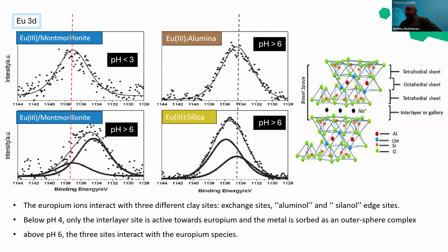So then what they decided, they did the same experiment on alumina and silica to mimic those two edge states that I was mentioning, with a high pH state. They found out that the europium deposited on the alumina is giving the peak at 134. And then in the silica, it is also giving 134, but it is also giving that 136 eV. So based on these two experiments, what they found out is that when the pH is high, the europium is binding in the interlayer state and in the two edge states. But if the pH is 3, it is only binding into the interlayer state. It is not binding in the edge state.